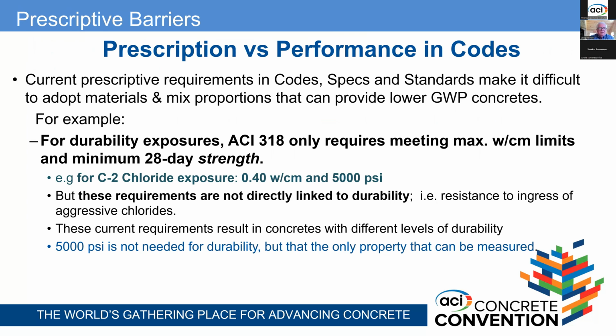For example, ACI 318, just as one example, for chloride exposure, exposure class C2, only says that to meet it, you have to meet a strength limit of 5,000 PSI or a maximum water binder ratio of 0.40. And apparently that gives you corrosion resistant concrete for structures, but those are indirect measures. Strength is an indirect measure of the water cement ratio, and water cement ratio is one input into what makes low permeability concrete that will resist chloride ingress. But they're not testing any direct measure of that chloride resistance.